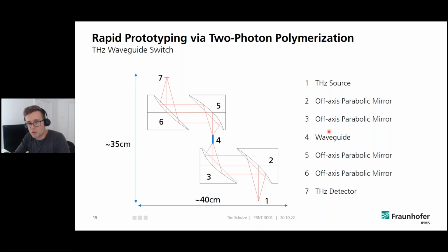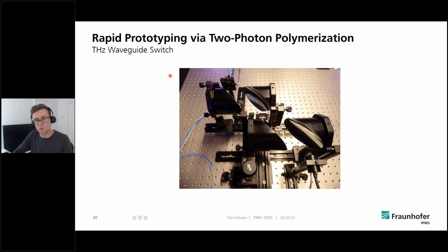And for the terahertz characterization, we used a really broadband terahertz source indicated here at position 1, and we just use mirrors to illuminate this broad terahertz spectrum into a waveguide at 4, and then just collect the same radiation again with mirrors until it gets into the terahertz detector. So this is how it looked like. Really simple setup that was able to characterize our different waveguide components.